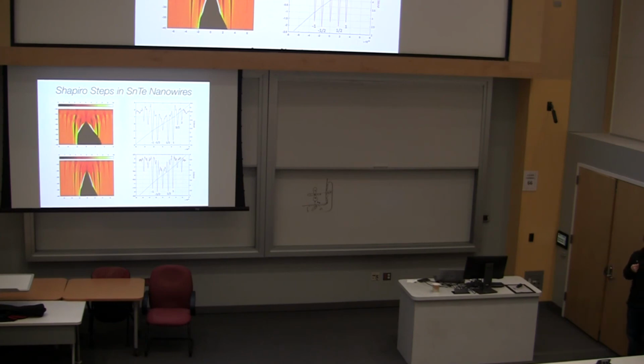tin telluride, you may know, undergoes a ferroelectric distortion that becomes more prominent as you thin down the materials. Since crystalline symmetry and its mirror symmetry is so important to the surface state, different domains of these different ferroelectric distortions are bound to do something to the band structure. So I'm very interested, what does that do to the Andreev bound states? And how do I deal with the interface between these two different ferroelectric domains? And I think once we have a good understanding of how that works, we'll be able to explain both the magnetic diffraction pattern and these half steps.